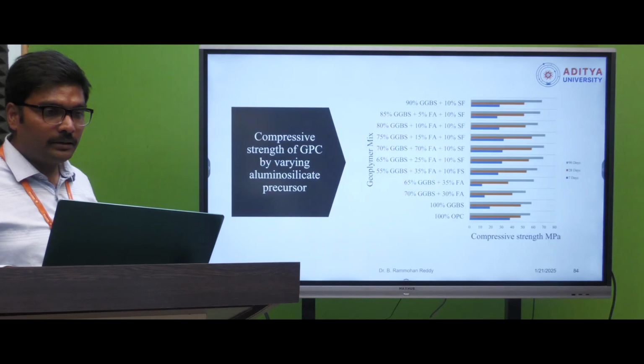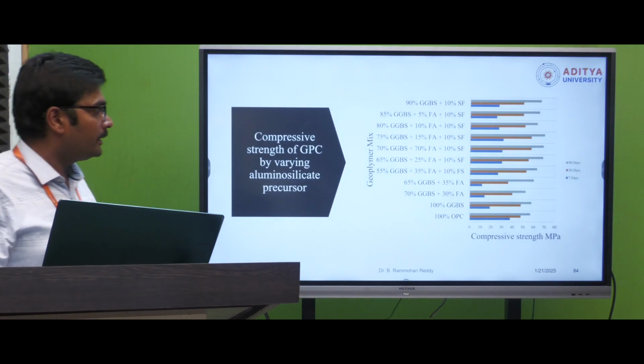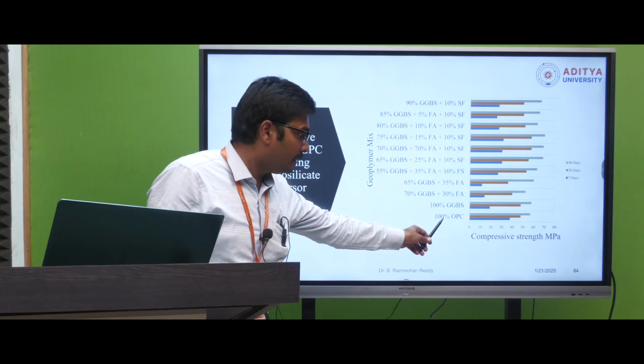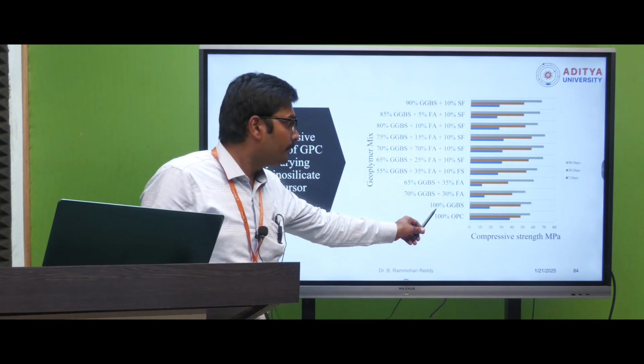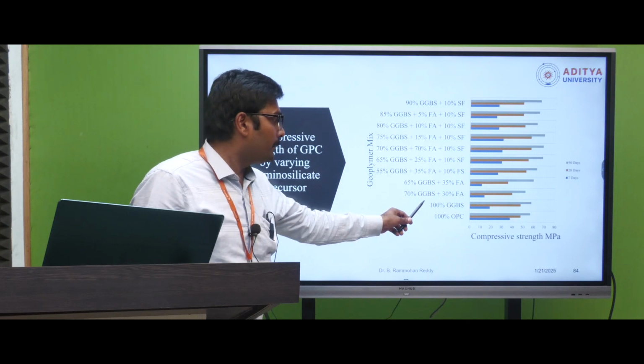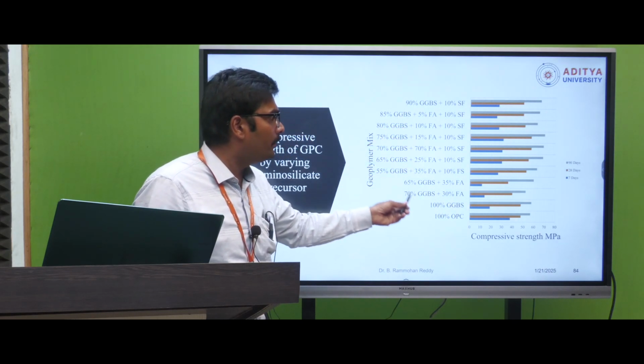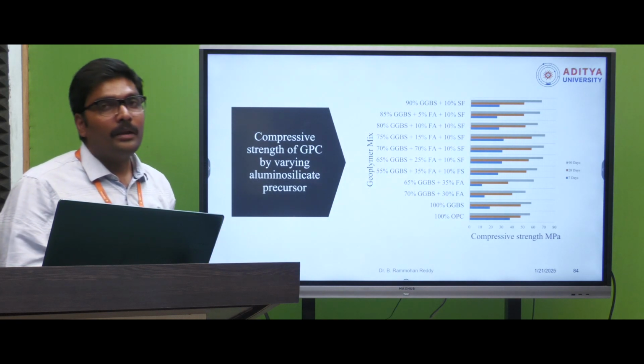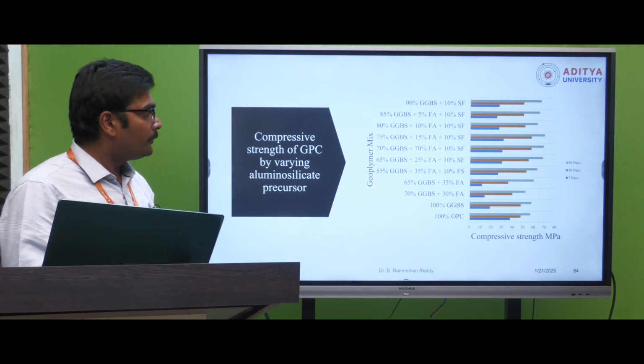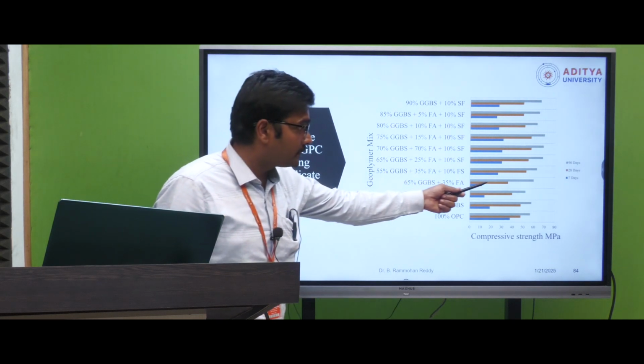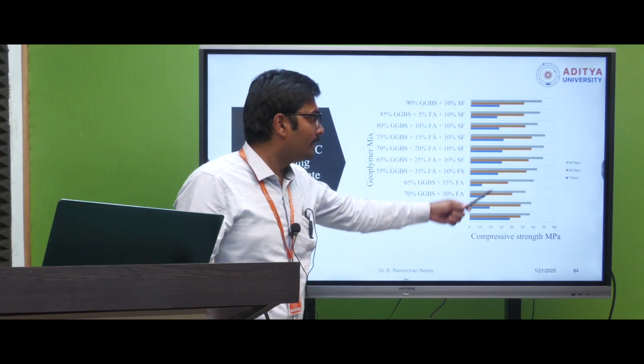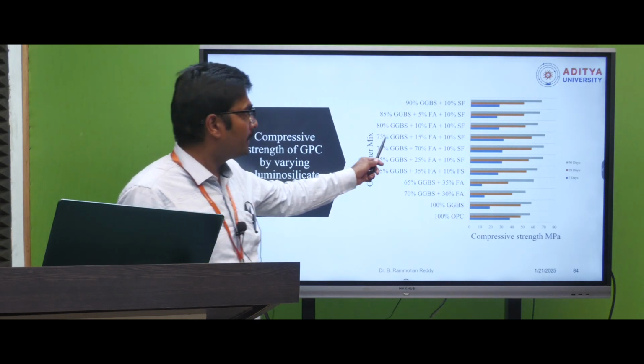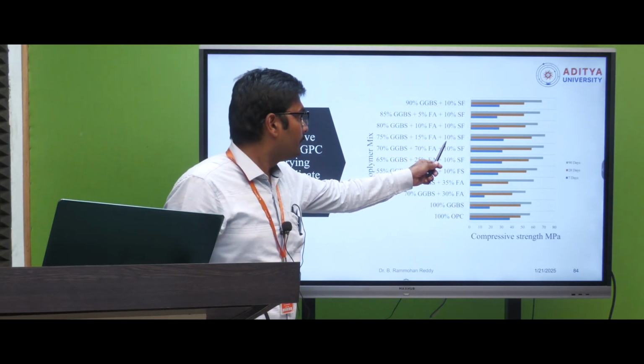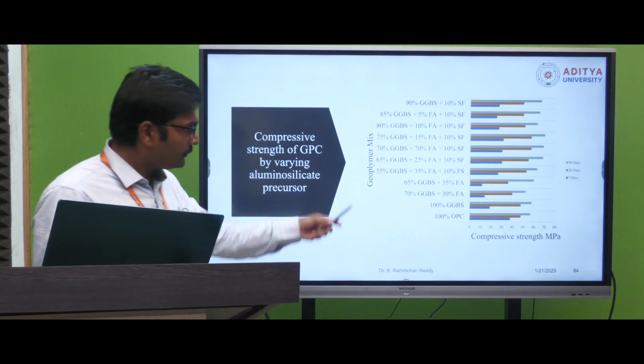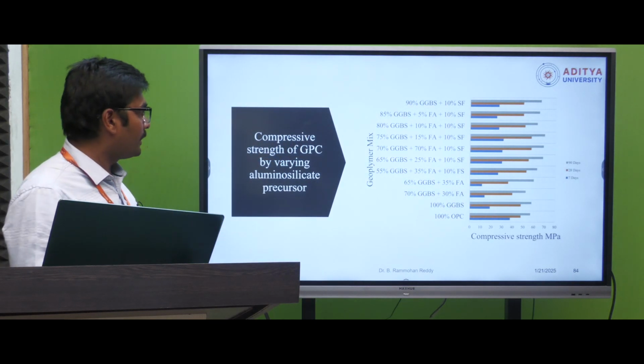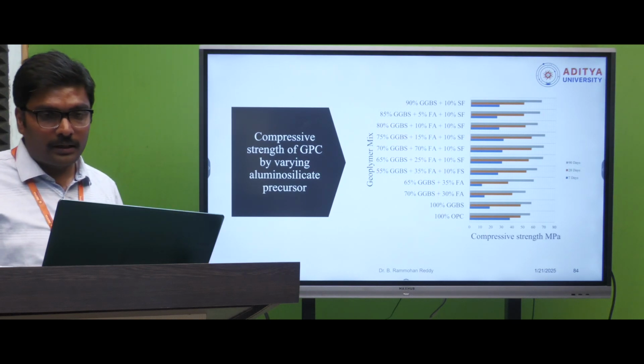Similarly, flexural strength. And another author presented the compressive strength for 100% ordinary Portland cement as a control mix, and 100% GGBS if used, and 70% GGBS and 30% fly ash. How the strength varies in these various combinations is presented in this diagram. And finally he concluded, having done the compressive strength for 7 days, 28 days and 90 days, that 75% GGBS, 15% fly ash and 10% silica fume produced better compressive strength. That was presented by one of the authors.